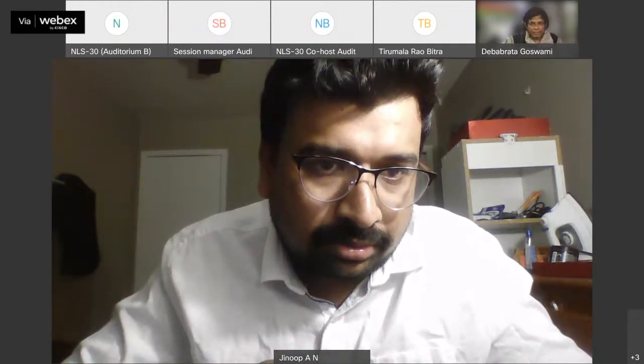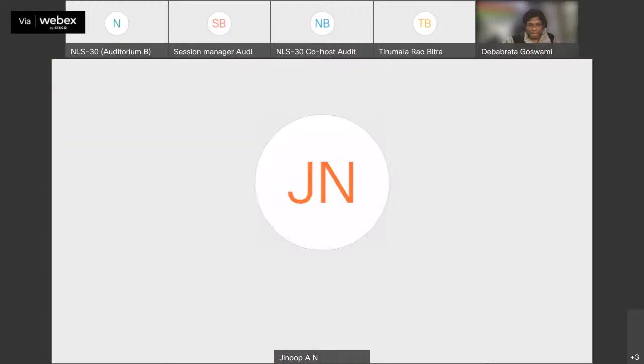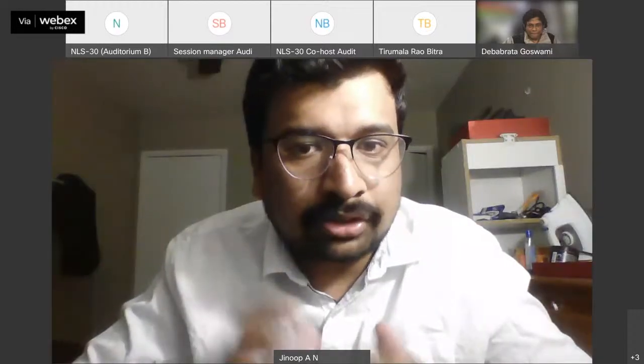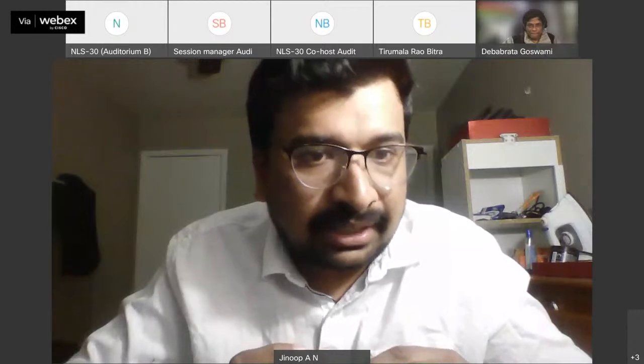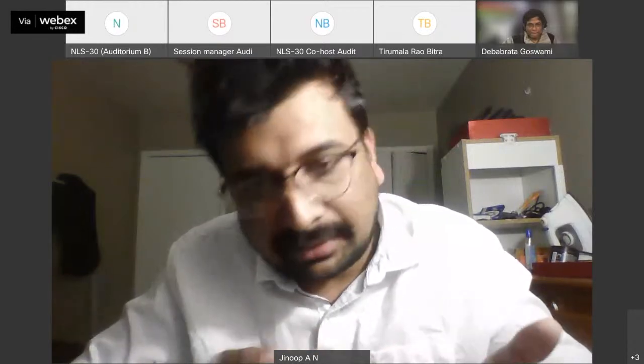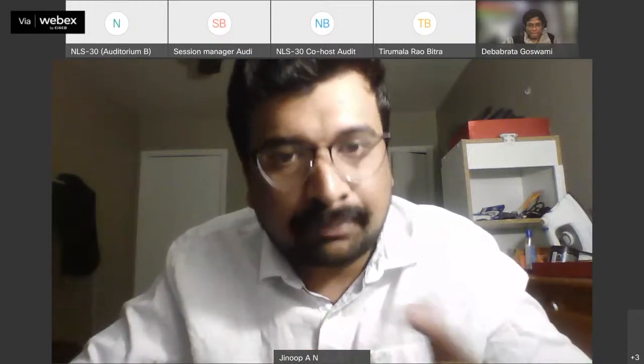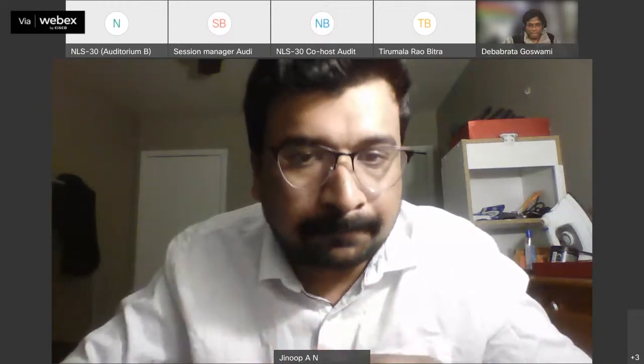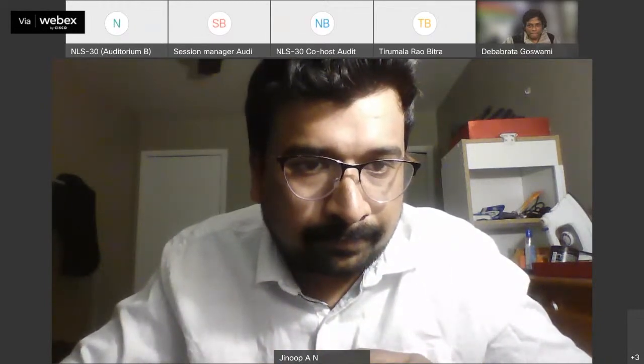See, conventional bulk versus this additive manufactured piece, what is the difference in strength? Strength is higher than the conventionally built samples in the as-built condition because of the finer grain structure and the higher dislocation density. But the ductility is poor, so we try to do heat treatment and post-processing to improve it further. Okay, Debu, you have a question?